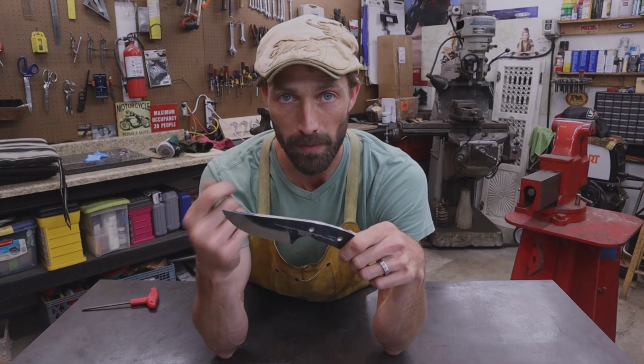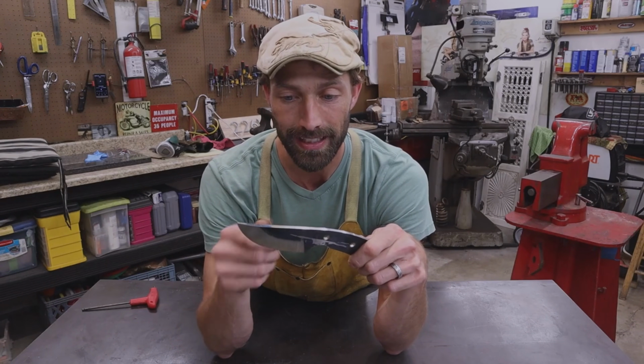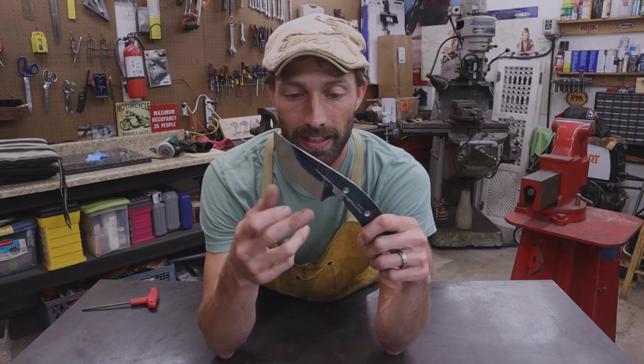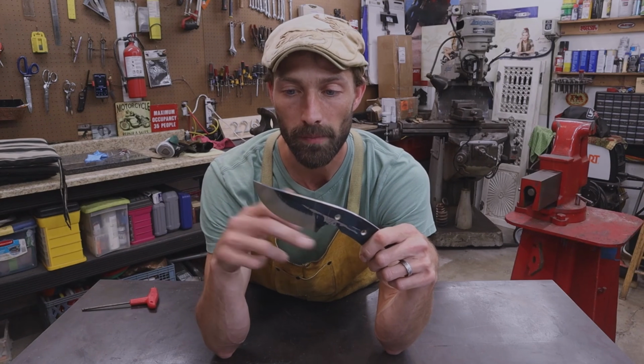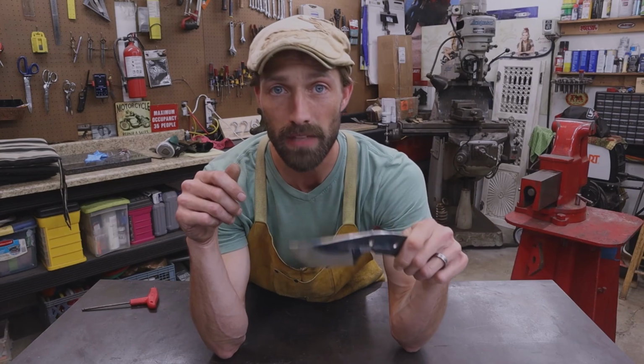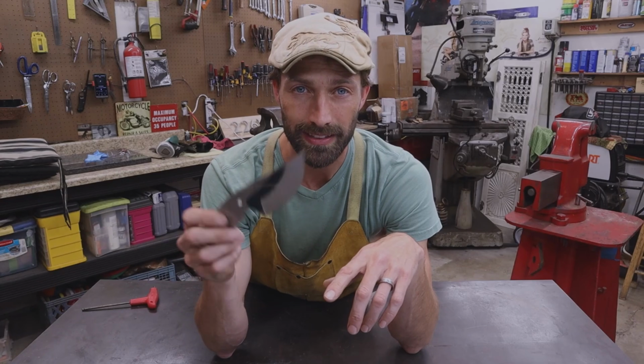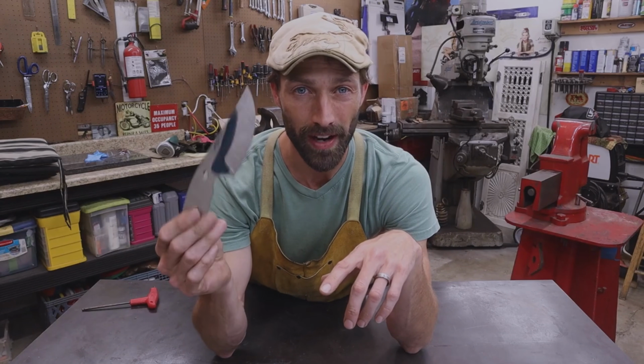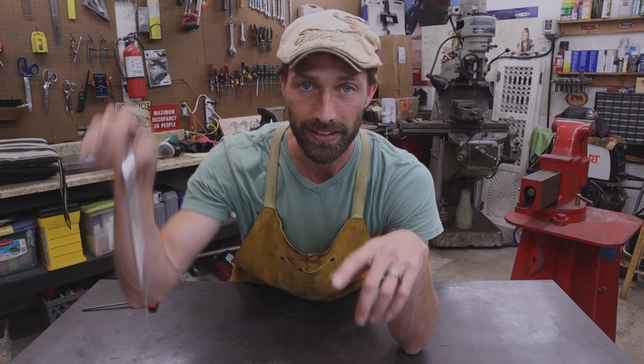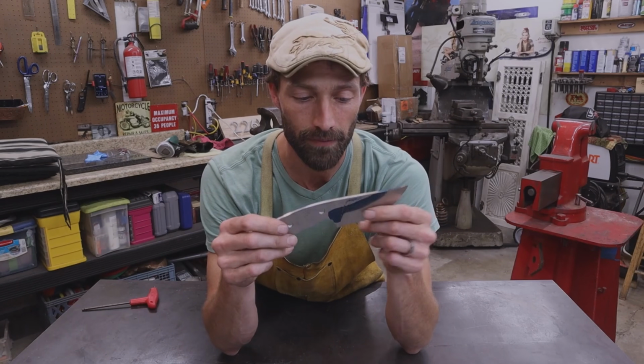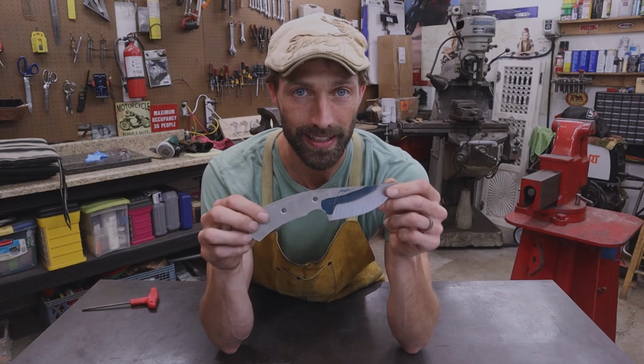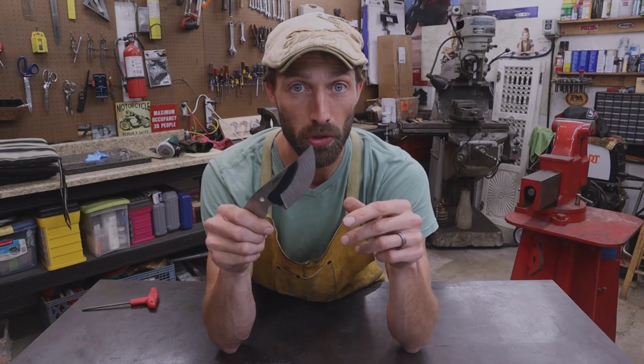You just keep testing it with the magnet, and once that magnet doesn't stick anymore, make sure you've got a good even heat all the way from here to here where the magnet doesn't stick, and then immediately go to your quench oil. You have to go immediately. I think the book says that you have less than 1.5 seconds to go from heat to quench to get the full edge hardness out of 1095. So that is super quick.